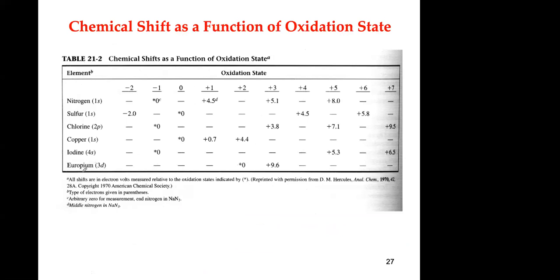And here, this is an old table from an instrumental analysis textbook that shows you how, depending on the oxidation state, how much the binding energy changes. In this case, you have sulfur, and it changes like 5 electron volts. And nitrogen here, 8 electron volts. So it's a big change.